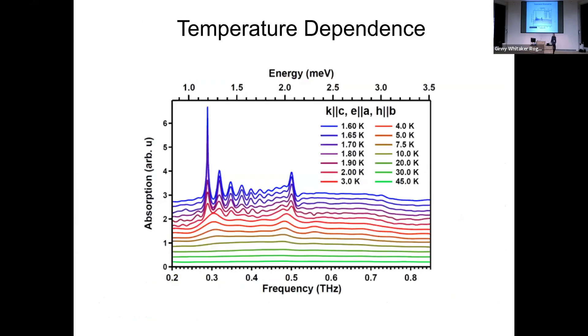In the absorption spectra as a function of frequency in the terahertz range — corresponding to a few meV — as we cool the system down, around 20 K we start to get long ferromagnetic domain correlations along the chains. Earlier neutron scattering showed that around 3 K the correlation length is about 100 lattice constants. It then goes through two low-temperature transitions into the antiferromagnetic state, and all of this sharp spectra suddenly appears. For those of us who do spectroscopy on solid-state physics, this is remarkable — we usually don't have many sharp peaks to look at.